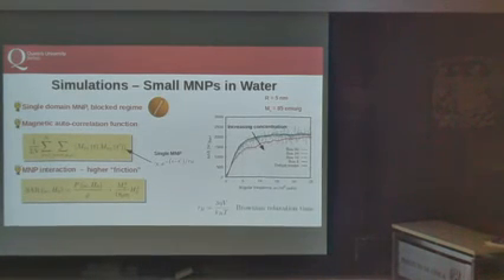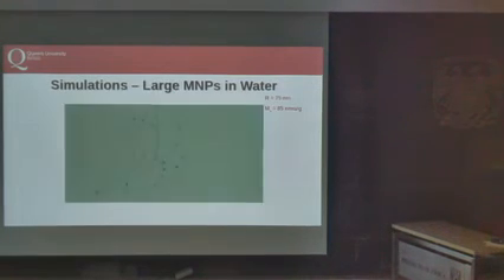The effect of the aggregation, in this case of the concentration, is to increase the friction, which makes sense. There is stronger interaction between the nanoparticles and then they relax more slowly. A little movie to finish up. This is for the simulation of the larger nanoparticles.